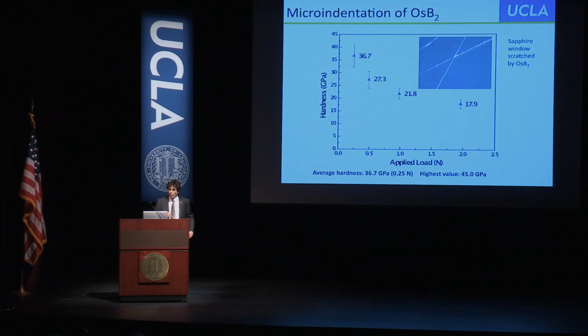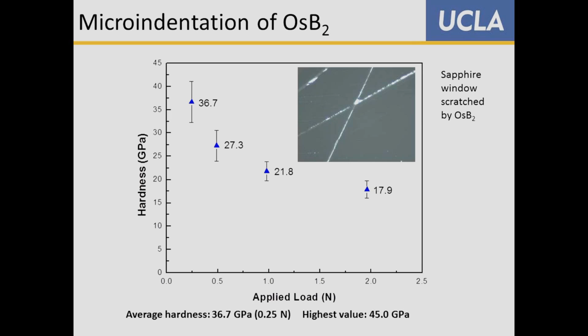Now, for hardness, you must have something that's incompressible, but it's not a sufficient condition. So the idea was we're going to put in short covalent bonds to get this to work. When we do this, if you look, this is a hardness versus applied load, and it's quite a hard material. In fact, it scratches sapphire. These are scratches we put in a sapphire window. Sapphire is 9 on the Mohs hardness scale. So we realized we're on to something very interesting.